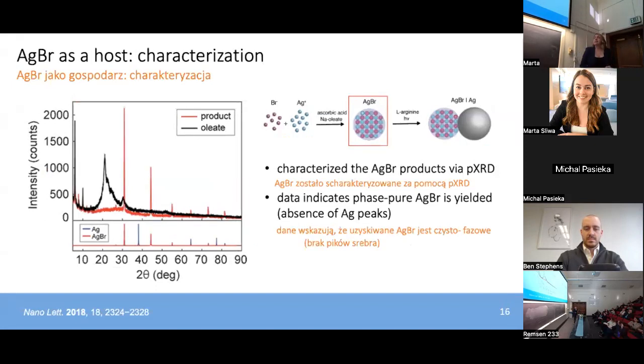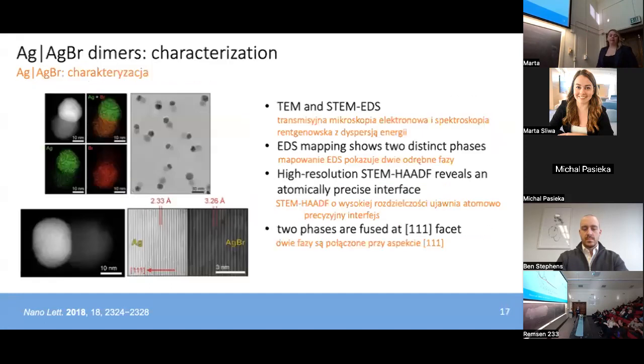So in this data, we see that there are no peaks. These blue peaks corresponding to metallic silver are not present in the data for the silver bromide hosts. This indicates to us that we have a clear two-step synthetic process, and the silver bromide is acting as a true intermediate. Only when we controllably expose those hosts to UV light and L-arginine do we get those silver-silver bromide dimers at the end.